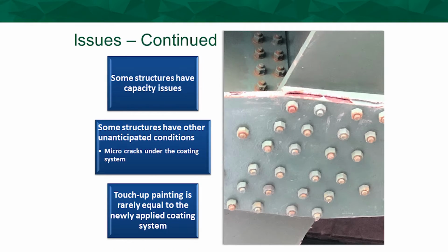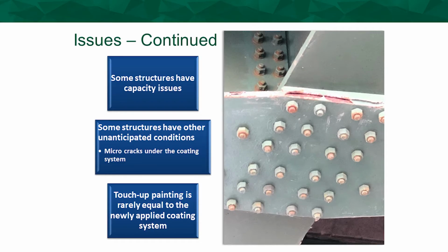Other issues, structural capacity. You want to make sure that the capacity of those structures can handle the equipment that is typically used for bridge painting, with your recycling abrasives, your dust collectors, the weight of the abrasive itself, and the containment system. Some of the unanticipated conditions, like micro cracking on structures that you don't see until that paint is removed from the existing coating that's been on the steel for many, many years and possibly coated several times, over coating. So you want to make sure that those are checked as well.